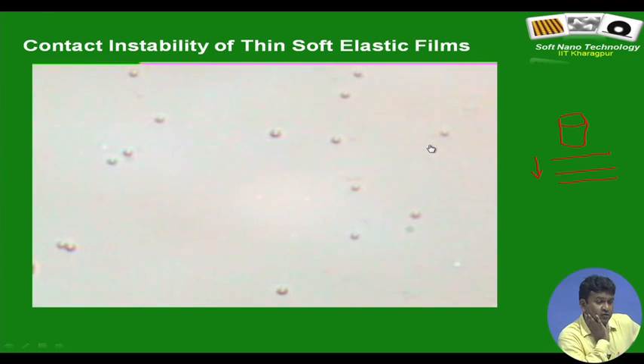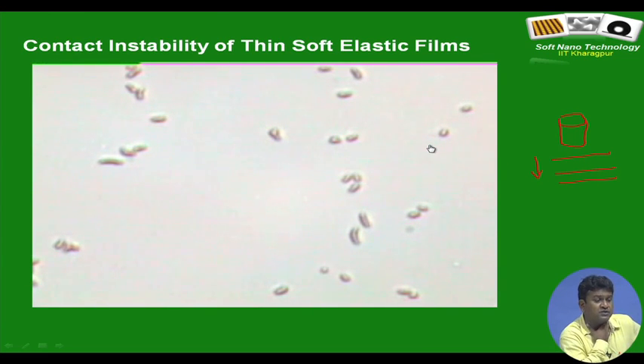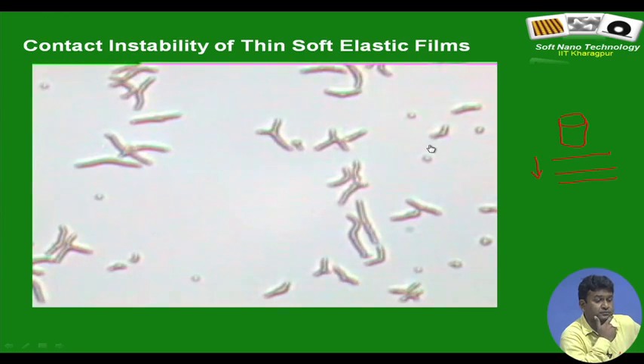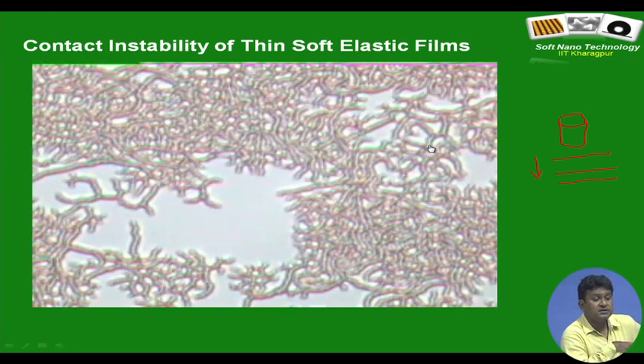But this is a real time image taken under a microscope. So what you have is, again, the situation we showed: here is the contactor, coming in contact with the film, and you are now observing from the top with an optical microscope. So see what happens. First, we see that initially we had a flat film and the contactor was far away. You see that some structures are appearing in the form of isolated columns, and the contactor is still approaching, and suddenly you see the whole area gets filled up with some structures.